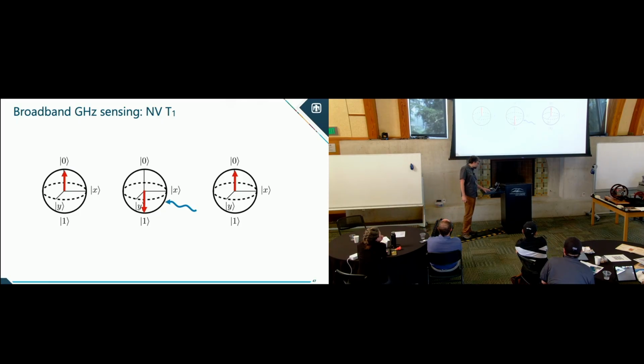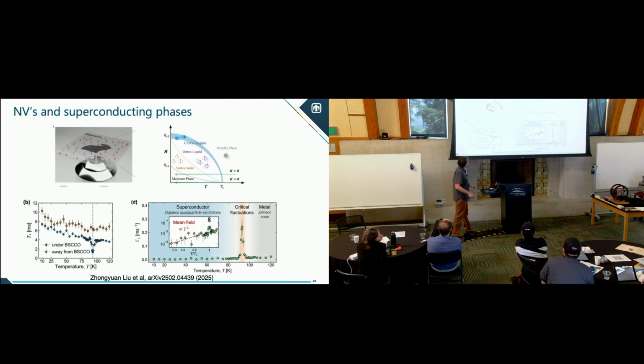There's a nice result recently from a friend of mine that was looking at superconductors on diamond. You can actually see an enhancement of critical fluctuations through a phase change right at the superconducting transition temperature. And this was with BSCCO on diamond, which is one of the high temperature superconductors. You can actually map out the phase diagram. You can say something about the pairing symmetry of your superconducting electrons by looking at the temperature dependence of this T1 value below Tc. And there's theory that backs this out, but this is coming from a fundamental science perspective of quantum sensing.